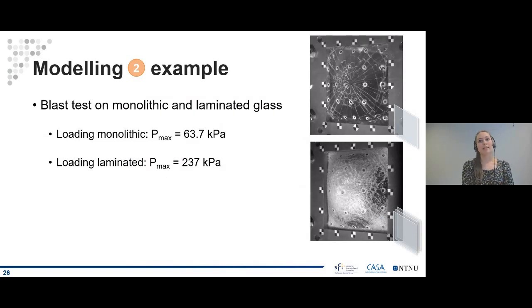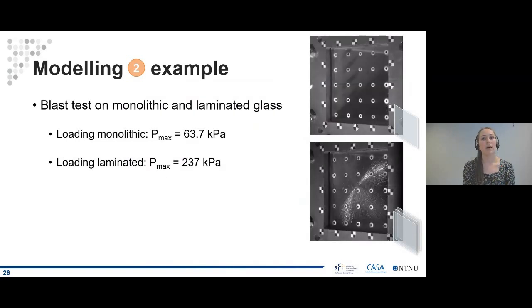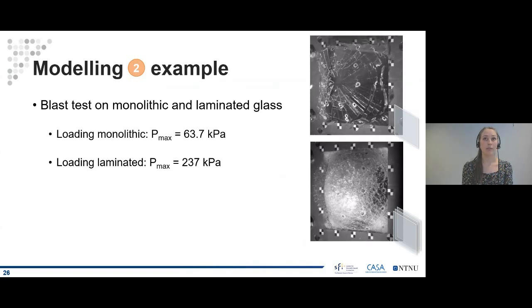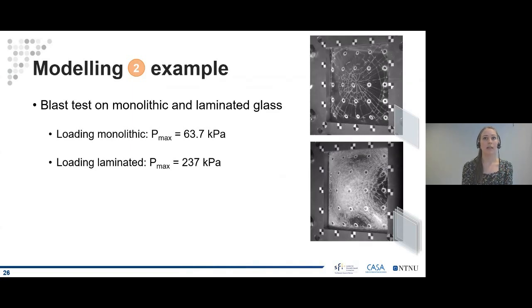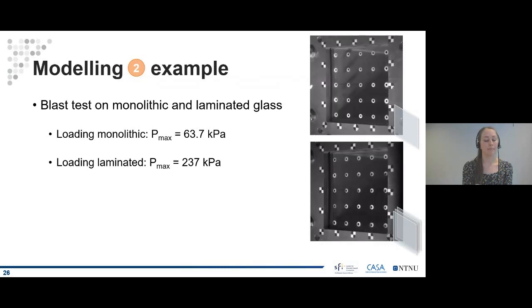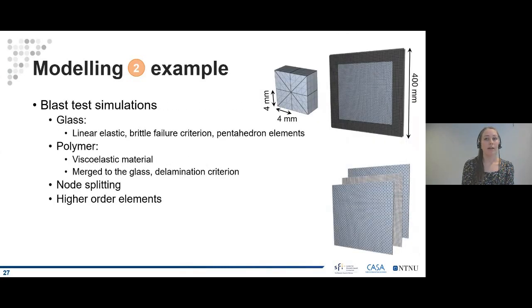Then I will show you some examples of finite element simulations. For this, I have simulated these two blast tests, one test on monolithic and one on laminated glass. In the finite element simulations, we model the glass as linear elastic with a brittle failure criterion. The glass also consisted of pentahedron elements. The polymer layer was modeled with a viscoelastic model, and it was merged to the glass. We also included a delamination criterion. And then we also used node splitting and higher order elements.